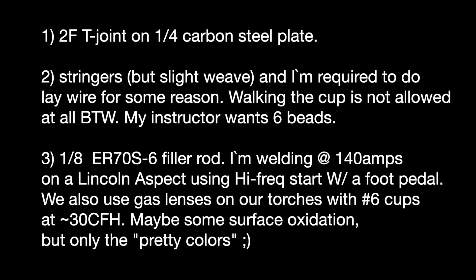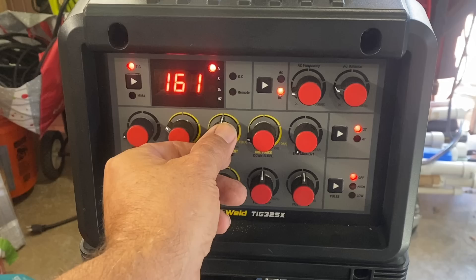I asked Connor a few questions on the YouTube comment so I could get some direction. Two things popped out at me, 140 amps and the fact he's using a number six cup with 30 CFH. Other folks chimed in and told him more like 15 to 20 CFH would be good on Argon and I thought that 160 amps would be more appropriate than 140. So I set it to 161 and let's put in that second pass now.